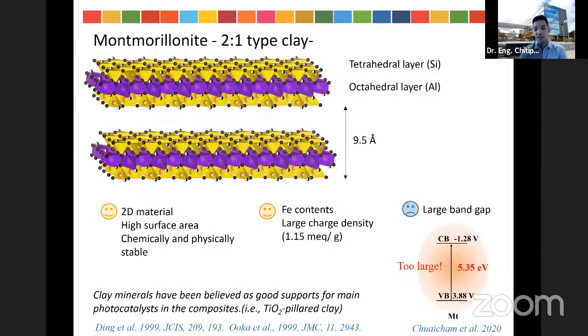Normally, clay mineral has been known as a good supporting material for photocatalytic composites. For example, TiO2 combined with pillared clay, because the clay is a two-dimensional material, it has very high specific surface area and high stability. So it can improve the growth of TiO2 on the surface of the clay minerals. And regarding the electrochemical property of the clay mineral, it has a large charge density, and natural clay often includes iron as an impurity. So the iron impurity might affect the photocatalytic performance or the photocatalytic reaction.